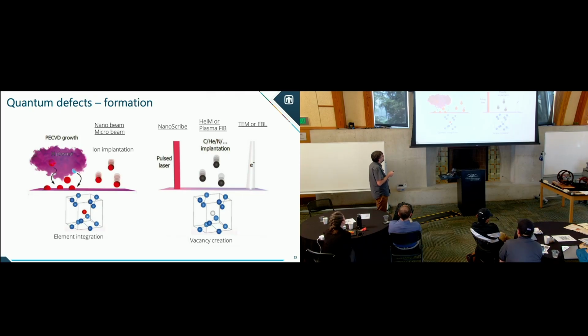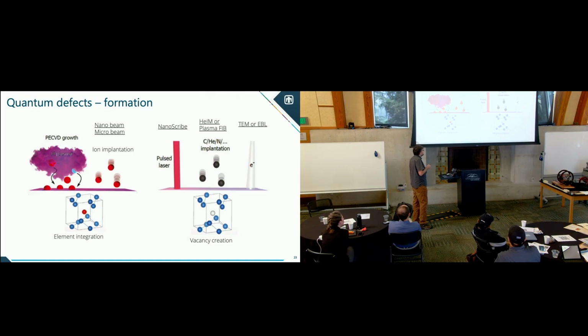And at Sandia we have capabilities to do this with nanobeams, though not necessarily for nitrogen. We'll talk about that later. But we have a focused ion beam system that, with custom sources, can focus ions with 50 nanometer resolution into different materials. All right. Now, once you have something in the lattice, with ion implantation that creates enough damage that you can easily anneal and then get nitrogen vacancies. But if you grow it with CVD, you only have nitrogen in the lattice, and it's a bit too clean. So then you can use different damaging mechanisms to also create vacancies, even locally. You can use a pulsed laser, and this is a fun thing we did using a 2-photon resist curing system at CINT. I used it instead to activate defects in silicon in that case, but diamond would work as well.